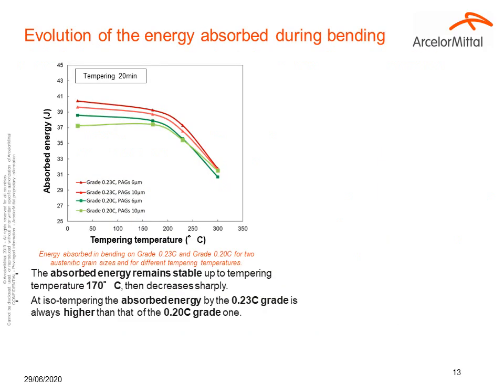Another representation of the evolution of the energy absorbed in bending is as a function of the tempering temperature. On this graph, the evolution for the two steels and the two heat treatments. The absorbed energy remains stable up to a tempering temperature of 170 degrees Celsius, then decreases sharply. Furthermore, for an isotempering temperature, the absorbed energy of the grade 0.23 is always higher than that of the grade 0.20. This is due to the higher tensile strength of the 0.23.